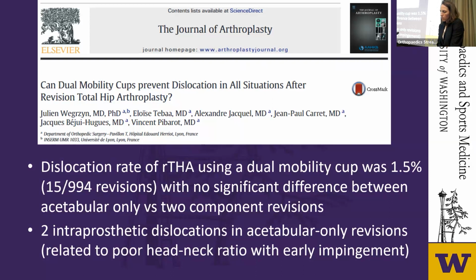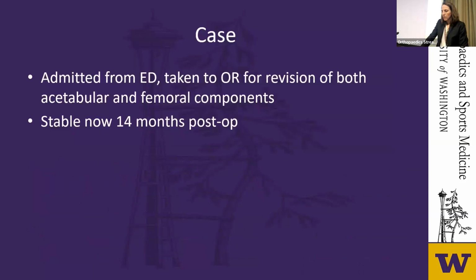And then the authors looked at all of those 15 dislocations in detail and evaluated for possible perioperative technical errors that might have contributed. And they found that 5 of these dislocations did have a technical error identified during review. So they concluded that while dual mobility has a very low dislocation rate, it doesn't compensate for potential technical errors, certainly.